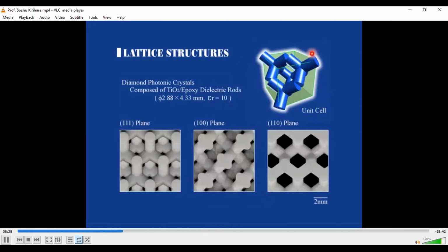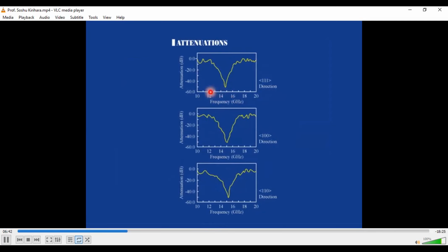This figure shows the transmission attenuation of the microwave. You can see that in all crystal directions, from 12 gigahertz to 20 gigahertz, a band gap forms. For example, a 15 gigahertz microwave is impossible to transmit in any direction. This means perfect reflection.